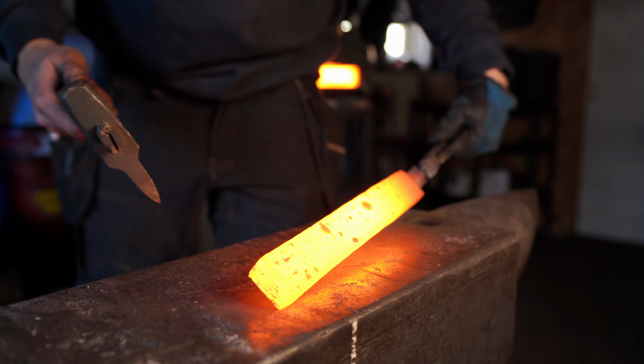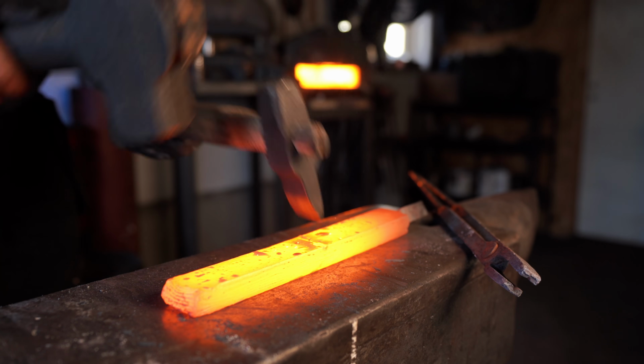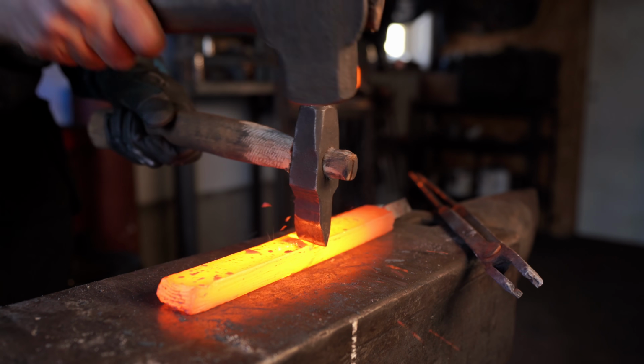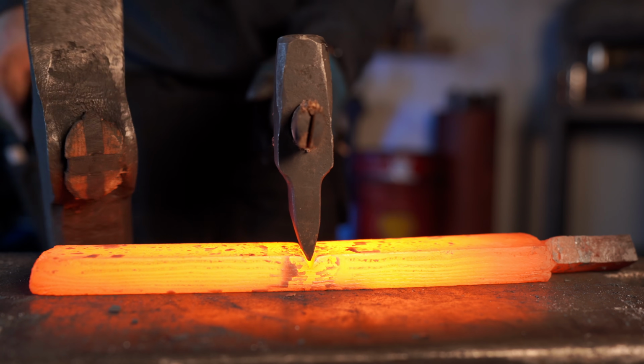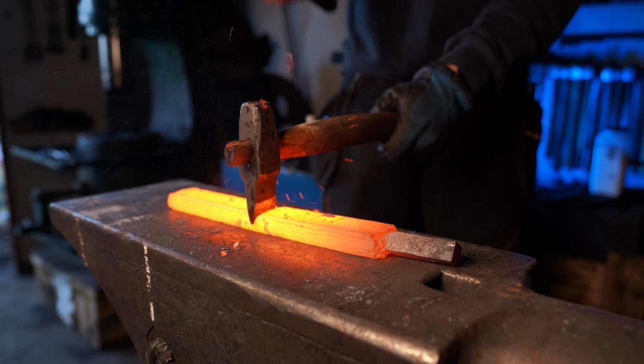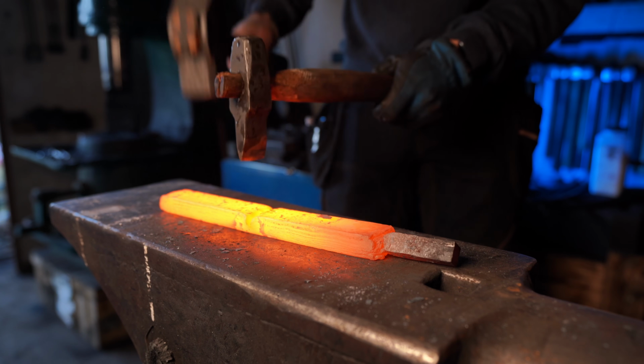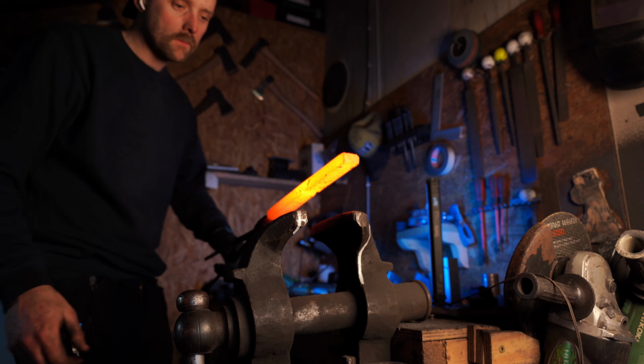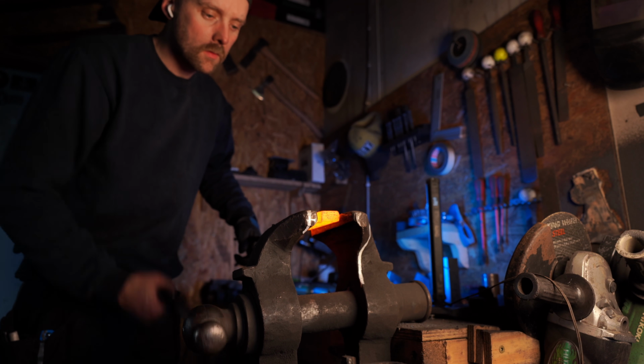Now, I want to increase the layer count of the billet. There's nothing wrong with 20 layers, but the pattern I have in mind really benefits from a higher layer count. And the way that I do that is simply by cutting the billet in half, restacking it, and reforge welding it. That takes it from roughly 20 layers to somewhere around 40 layers.